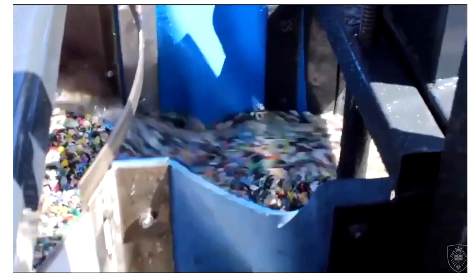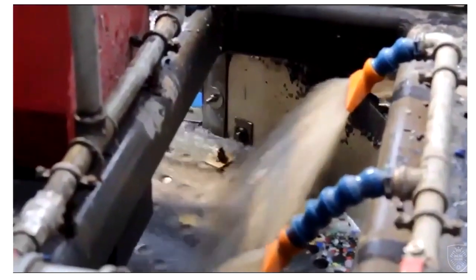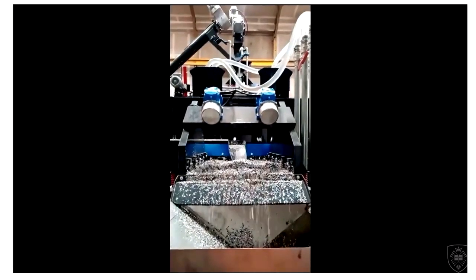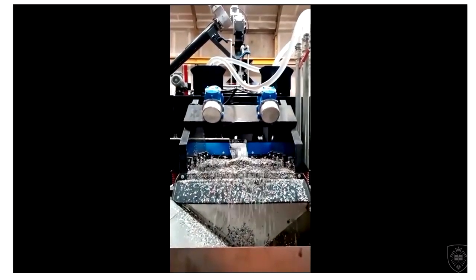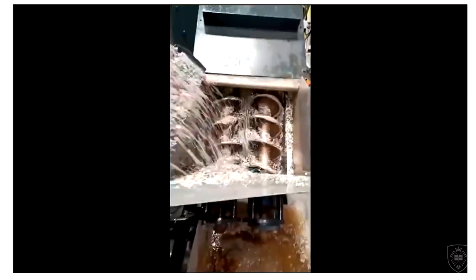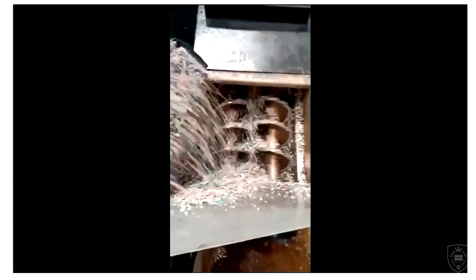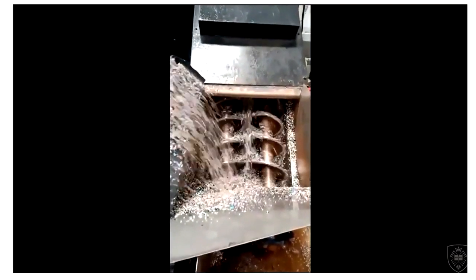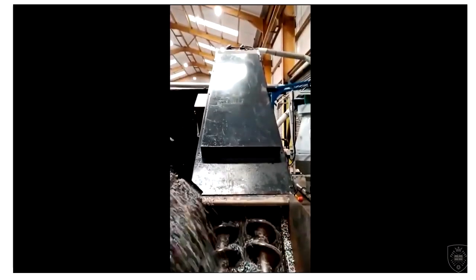Here's just inside the tank, the oscillation up and down. There's the plate that you can see, and this is just the back of the tank, the polypropylene coming out the back of the tank. And then it goes into a screw conveyor where we dry it, we dedust it. Here's one of the guys just taking a sample to show you the purity. If I'd stop that at the right place, you can see how many particles are at the top and how many particles are at the bottom. We can get about 95% purity.